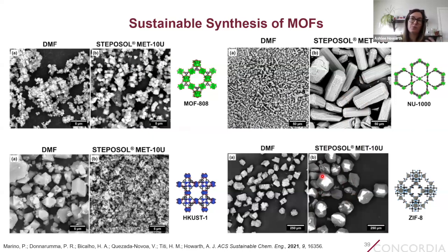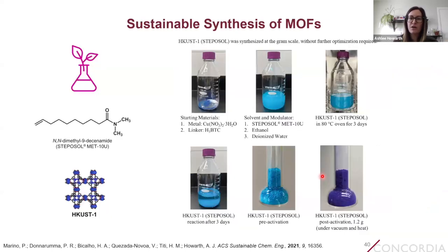So in addition to replacing DMF with a plant-derived, more sustainable solvent, we may have also stumbled upon a solvent that allows us to make large single crystals of MOFs, which can sometimes be a significant fundamental challenge in the field. We also are able to make MOFs in Cyrene on a large scale. And when I say large scale in our lab, that means a 1 gram scale, since normally we work on the 30 to 50 milligram scale.